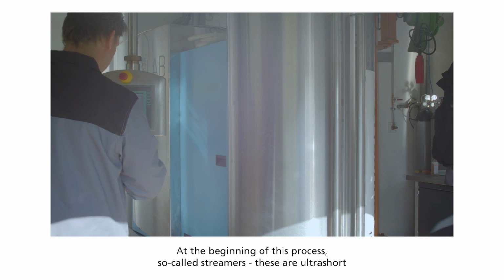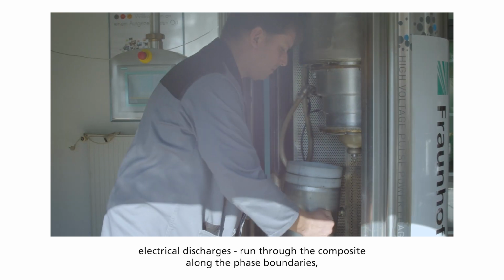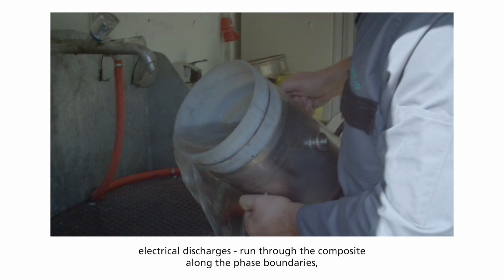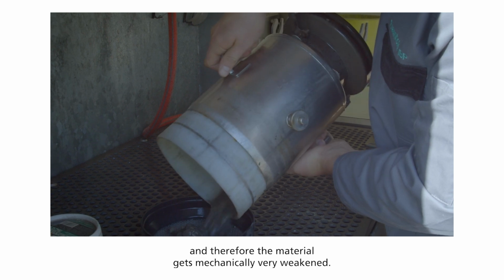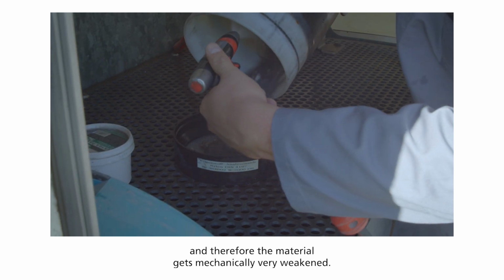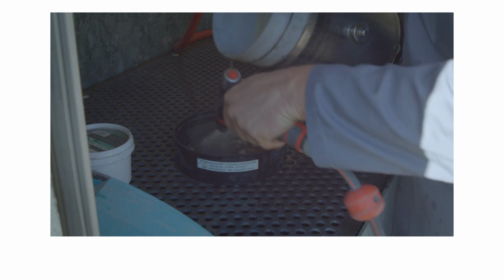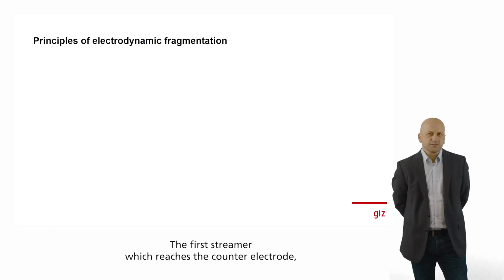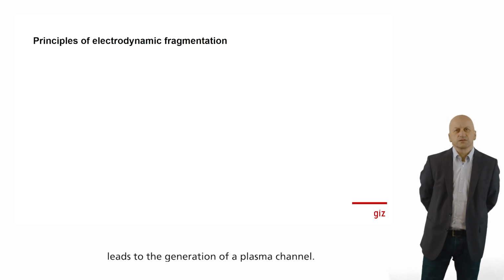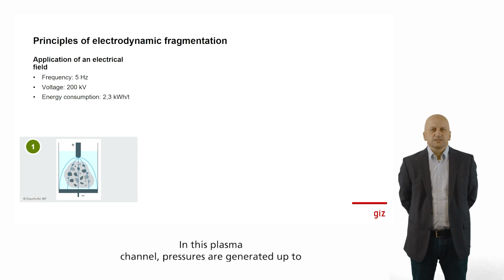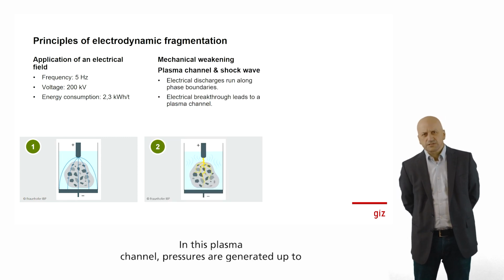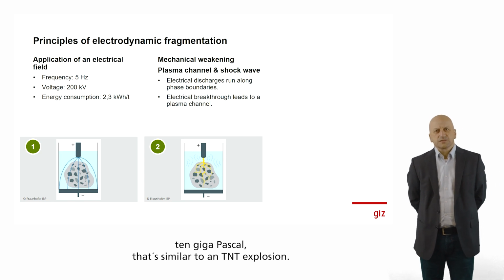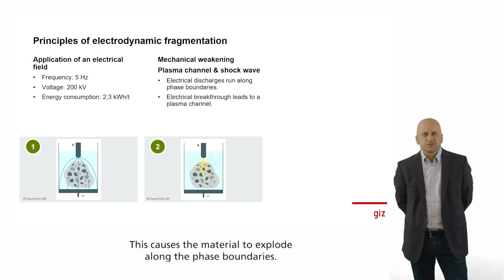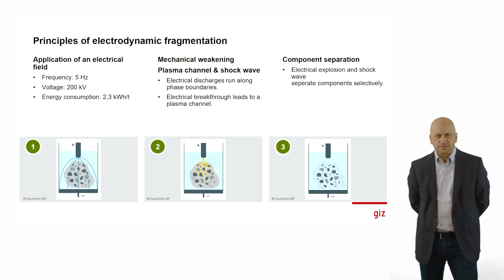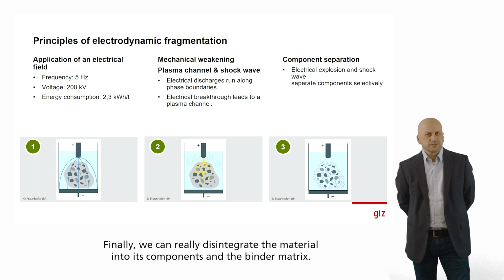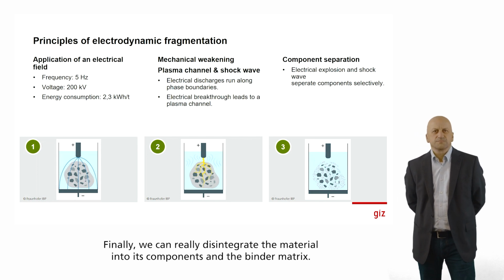At the beginning of this process, so-called streamers, these are ultra-short electrical discharges, run through the composite along phase boundaries, and therefore the material gets mechanically very weakened. The first streamer, which reaches the counter electrode, leads to the generation of a plasma channel. In this plasma channel, pressures are generated up to 10 gigapascal. That's similar to a TNT explosion. This causes the material to explode along the phase boundaries. Finally, we can really disintegrate the material into its components and the binder matrix.